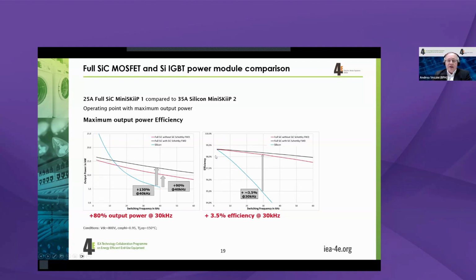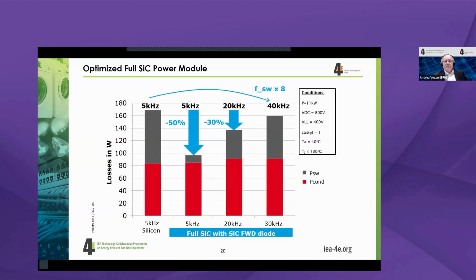As you can see, when we are at very low switching frequencies, like 4 or 5 kilohertz, there is not such a big difference between these two semiconductor devices. But as soon as you increase the switching frequency, we see a decrease in efficiency, and we therefore have an advantage of silicon carbide. Again, the silicon carbide module with the freewheeling diode has a slightly better efficiency. So what we get from this is that silicon carbide allows us to increase switching frequency without too much penalty in losses. And this is something which is shown here a little bit.